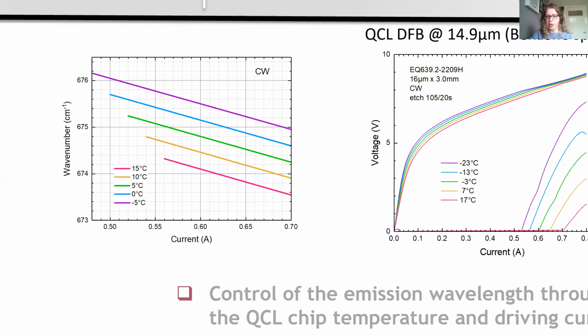Typically over a long integration time of seconds, the line width is typically less than 200 megahertz. This is actually a very conservative estimate, and in fact, I'll show in the next slide that there has been work to demonstrate this laser for use in high resolution spectroscopy, and we've managed to resolve species of line width down to 30 megahertz. So that's an order of magnitude smaller than this typical conservative estimate of 200 megahertz.